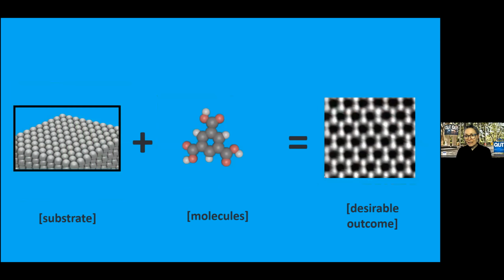But of course, we can use judicious choices of our substrate and our molecules at the molecular level and come out with fairly predictable, robust outcomes that are actually very useful to us. And this is just a quick overview of one of the systems that's really a darling of people that work with molecules on surfaces. This is benzene 1,3,5 tricarboxylic acid, or trimesic acid. And when we use a non-reactive substrate, we're able to take advantage of self-assembly to create a desirable outcome.